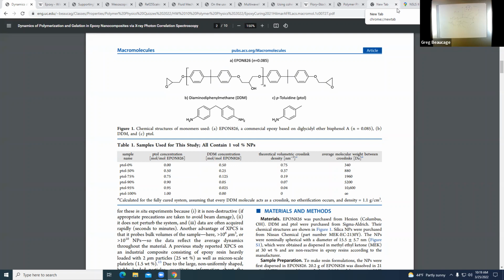The measurements you can do are NMR, and you can measure the number of those epoxide rings that still exist, the number of the amines that are still there, the number of the single ones, and the number that have totally reacted. So you get numbers for all these. You can get, locally on an atomic scale, an exact measure of how this reaction is going. You can say, for instance, what's the probability that one of these things will react? You can get a probability for all these reactions to happen, and then you can figure out how this network grows.